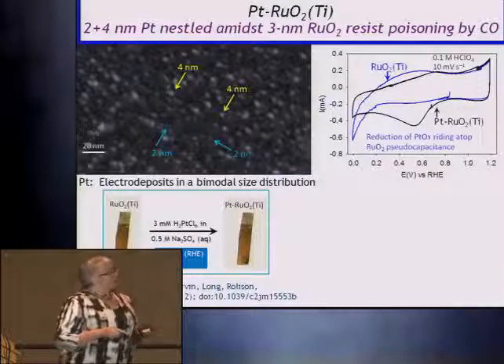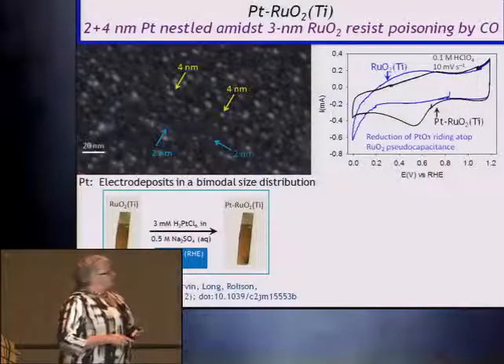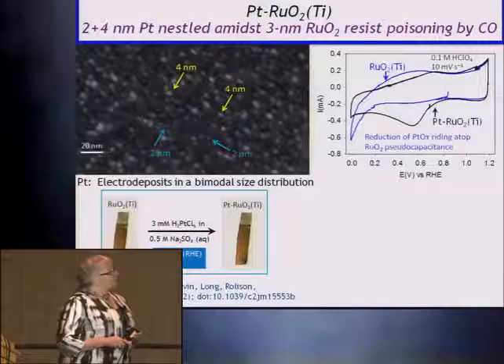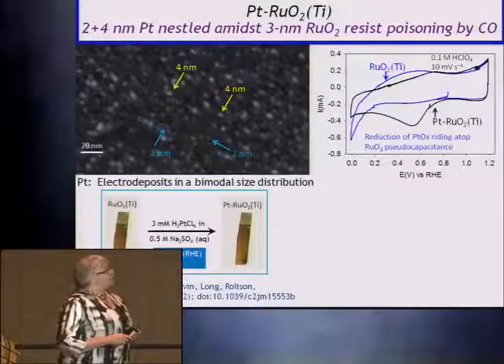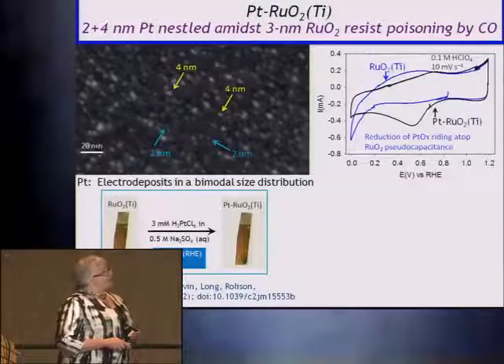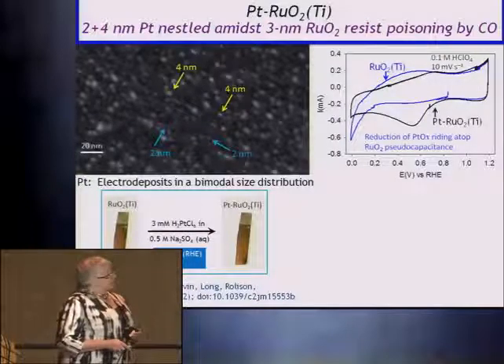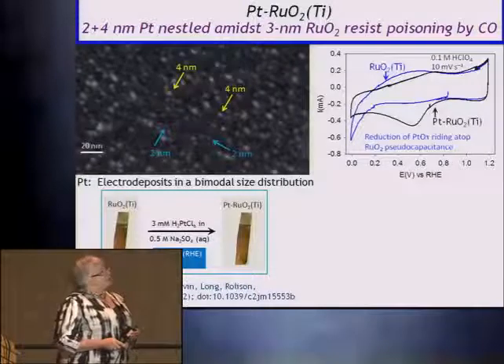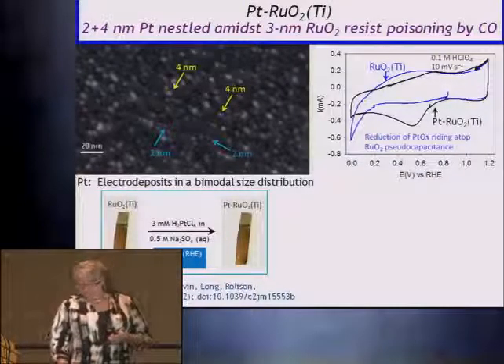Now, in aqueous perchlorate, with just the ruthenia titania, you see a lot of capacitance, so you haven't lost that by putting it on the titanium support. And once the platinum is there, it's not a well-defined hydrogen absorption and desorption, but you know the platinum's there because you can see the oxide stripping peak.